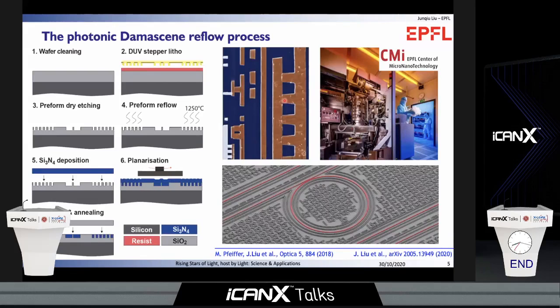Next, I will show you the silicon nitride fabrication process developed during my PhD work. To fabricate the silicon nitride photonic integrated circuit, we developed and optimized the photonic Damascene process over the past few years. This process was actually inspired by the copper dual Damascene process, which people use to make copper interconnect circuits. In this process, we use standard CMOS technology, such as deep UV stepper lithography, dry etching, low pressure chemical vapor deposition, chemical mechanical planarization, and thermal treatment. I should mention that all these steps are implemented in our EPFL clean room facility.